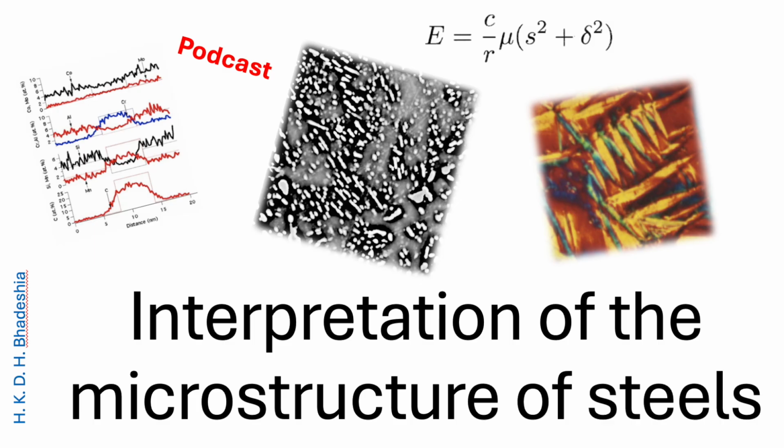Okay, so that's our focus. The two paths out of austenite, which has that face-centered cubic, or FCC, structure. And the phases that result are things like ferrite, the alpha phase, BCC, and the intermetallic cementite, theta. Right. And their mixtures like pearlite. But then you get into the stuff created when you cool too fast. The non-equilibrium phases. Right. Martensite, bainite, and that interesting hybrid, Widmanstätten ferrite.